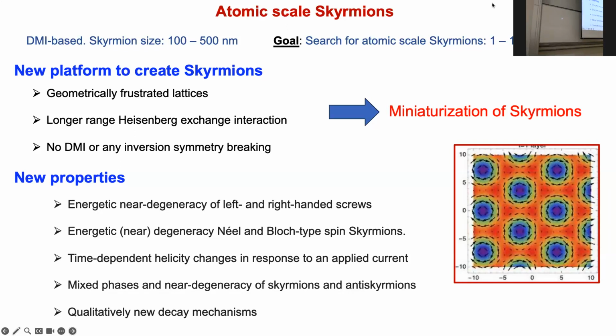in cranking up the Dzyaloshinskii-Moriya interaction, but rather creating a completely new paradigm. That is, instead of looking for DMI-driven skyrmions, we are now looking at geometrically frustrated lattices with longer range Heisenberg type interactions and absolutely no DMI. So the combination of geometric frustration and interaction frustration driven by long range Heisenberg interactions results in miniaturization of skyrmions.